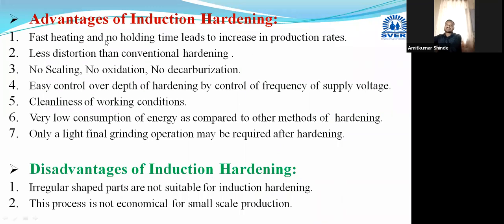That is very fast; heating is obtained within 2 to 5 minutes. Heating is completed, as there is no minimum holding time. Production rate is very high in this induction hardening method. Then very less distortion as compared to the conventional hardening methods, and no scaling or oxidation; decarburization is very less or very minimum. Then we can easily control the depth of hardening by controlling the frequency of alternating current.